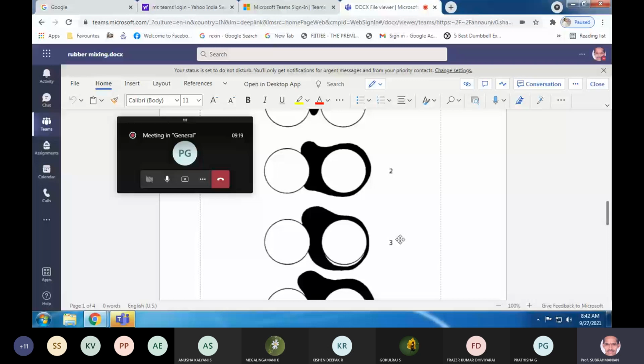In case of a rubber like NR, which undergoes reduction in the molecular weight, short chains are formed. What do these short chains do? They add to the surface energy of the rubber. So the powdery additives are at a very high surface energy, and the short chains in the rubber also add to the surface energy. So there is an energy balance, and as a result, wetting happens.